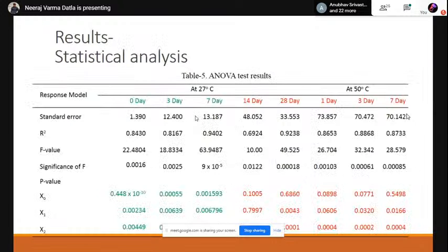And this is the ANOVA test results. So from this we can see up to 7 days the p values are satisfying the 95% confidence level, but for prolonged periods of 14 days and 28 days, or at high elevated temperature, the p values are not satisfying the 95% confidence level. Those values are greater than 0.05. So we can suggest that the linear analysis is applicable only up to 7 days of curing, and it is not applicable for a prolonged period. For that, we need multiple linear regression analysis or some advanced techniques.